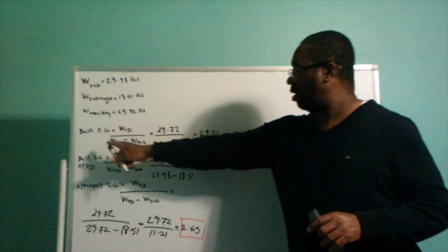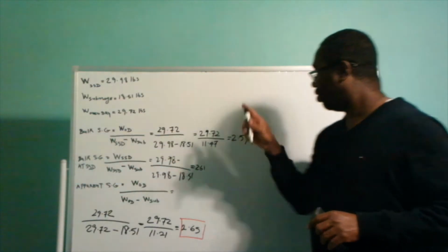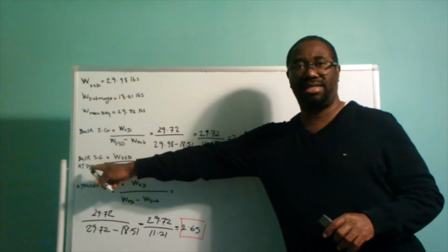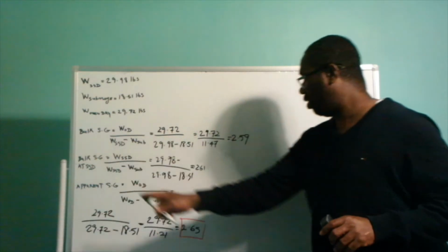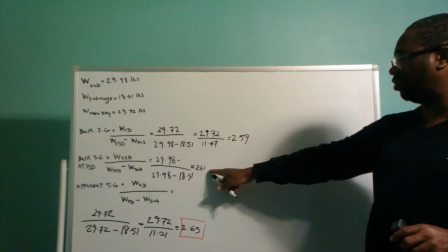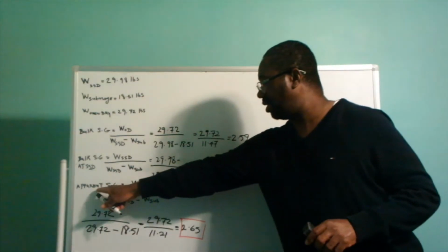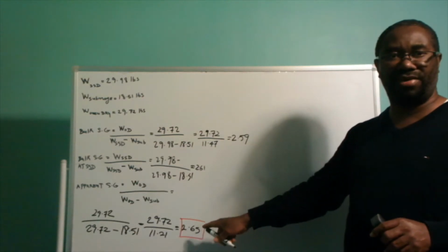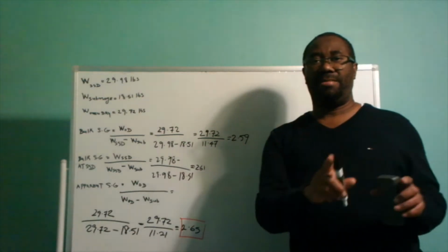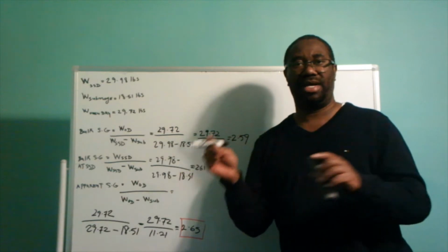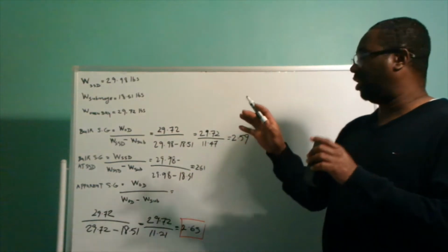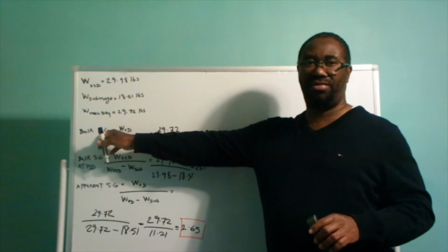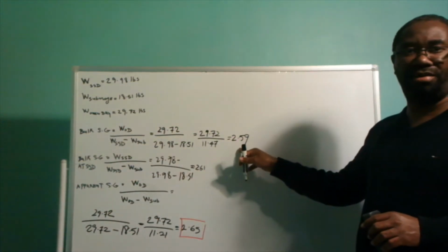So it is the bulk specific gravity 2.59, the bulk specific gravity at SSD, at saturated surface dry, which works out to be 2.61, and the apparent specific gravity works out to be 2.65. So my mistake, and I apologize for that miscalculation. So you can go now and see the correct calculation for the bulk specific gravity, which is 2.59.